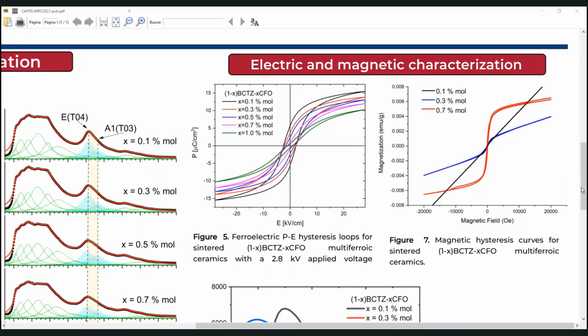Conversely, as the concentration of cobalt ferrite in the ceramics increases, an increase in the saturation magnetization of the ceramics is observed, but the coercive field is practically the same in each cycle of figure 7. This change makes us notice the effect of the increase of the dopant on the ferromagnetic characteristics of the ceramics.